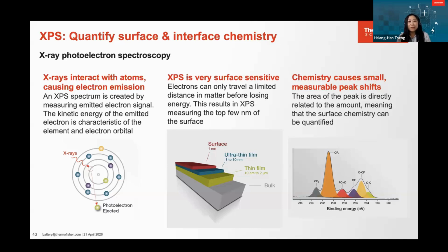So basically, XPS involves exposing the materials to a beam of X-ray photons, and the interaction of the X-ray photons with an atom can cause emission of electrons. And because electrons interact very strongly with matter, when the electrons travel, they can only travel a very short distance, around several nanometers, before they lose all of their kinetic energies. So that is basically the underlying principle that makes XPS very surface sensitive and also gives rise to an analysis depth of typically just around 10 nanometers thick.